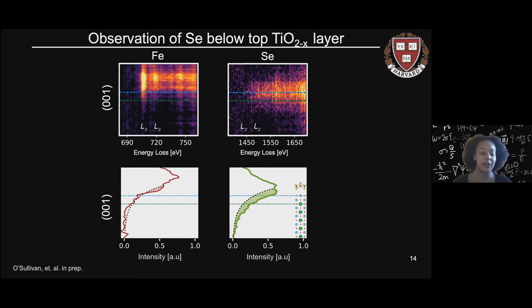It's important here that we have the iron signal as well in conversation with the selenium signal, because the iron signal sort of preemptively answers the question, well, is the whole monolayer just shifted further down into the bulk? And the iron signal serves as a sort of control for us to be able to say, no, clearly the monolayer resides higher as indicated by the iron peak, but there's an unusual, unexpected amount of selenium shifted lower into the strontium titanate bulk.